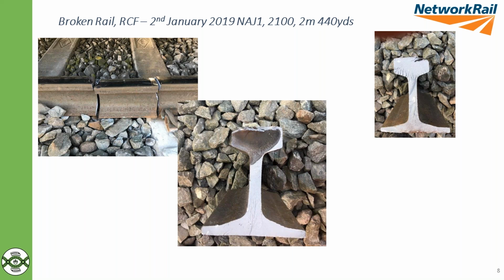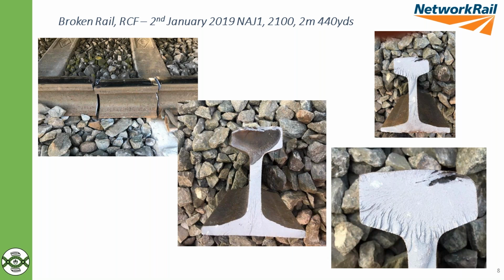But you can see there, once you've got a cantilevered rail from the first break, the risk of a secondary break increases dramatically. And even a small defect that may be in that vicinity can result in a secondary broken rail. We were very fortunate in this location. We didn't lose a longer length of rail and potentially a derailment that could have happened. So yes, it's something there, and a close up there, that's the secondary break. You can just see the small RCF cracks, nothing particularly large in that situation, but enough to cause a weak point so that the cantilever rail failed.